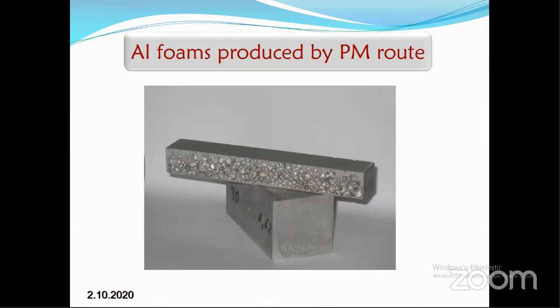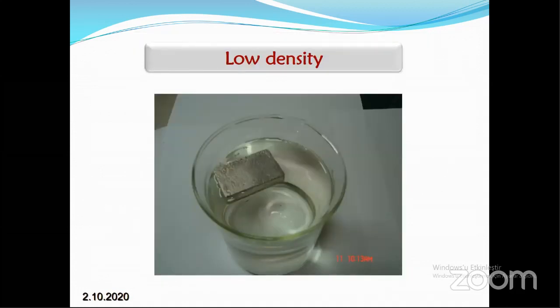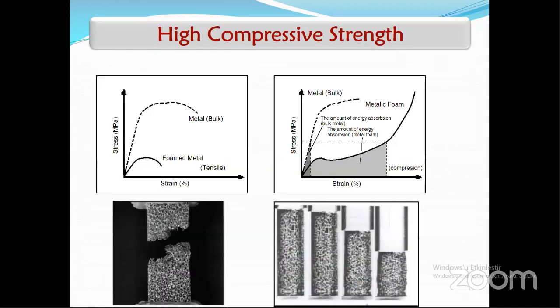These are aluminum foams produced by the powder metallurgy route. When you look from the outside, it looks like normal aluminum, but when you cut it, the cross-sectional area contains lots of porosity. It looks like a sponge. Because of this porous structure, it has very low density. That is important. This is a sample produced in our lab. The density was about 0.6 gram per cubic centimeter. The sample can float on water easily. That's why this material is very important.